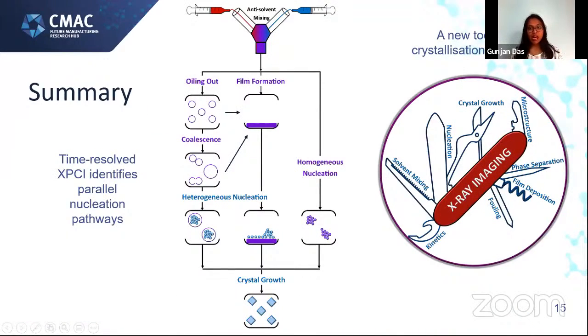So my summary is we were able to observe three potential pathways to nucleation. One of them was via an oiling out path, where these spherical droplets were joining together and coalescing together, leading to heterogeneous nucleation. The other pathway was through the 2D film phase, which, since lovastatin is such a huge molecule, started forming due to the attraction between the outer reactor tube and the actual molecule. And the final pathway was the homogeneous nucleation, which we have observed as white dots in the still image I have shown you. And all three, of course, lead to crystal growth.